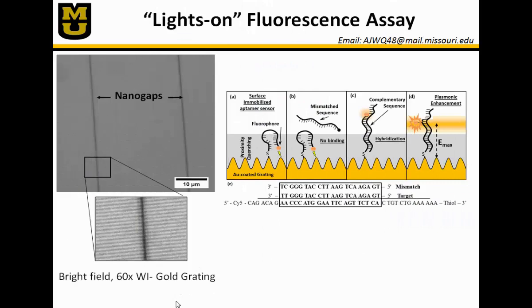So to test this fluorescence enhancement platform for a sensor application, we developed this lights-on fluorescence assay, where we custom designed a 42 base pair single-stranded DNA chain with a thiol group located on the 3' and a Cy5 dye located on the 5'. We immobilized this DNA onto our gold grating, and under solution conditions, this DNA will form a hairpin, and due to the proximity of that fluorophore with the gold grating, the fluorescence will be quenched, or you won't see any fluorescent signal.